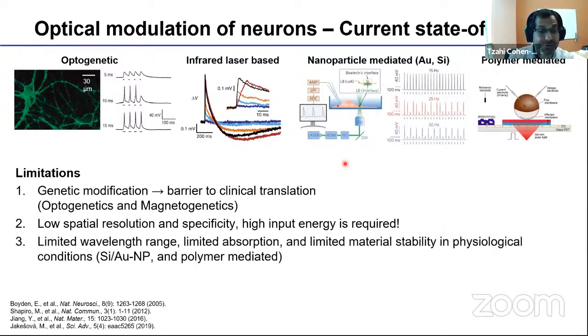Some of the limitations of nanoparticles or even polymer-mediated approaches are related to limited wavelength. These materials are not a broadband absorber, for example. Limited absorption means that you'll need to crank up the energy or the intensity of your light source to get an effect. And there is limited material stability, so polymers or even silicon particles can decompose after some time once injected. For some applications you want a transient effect, so you want the particles in and then they disappear after a few weeks. That may be an advantage, not just a disadvantage.